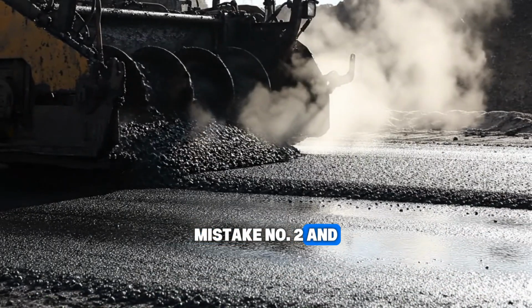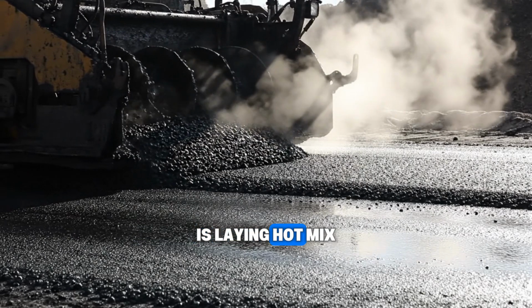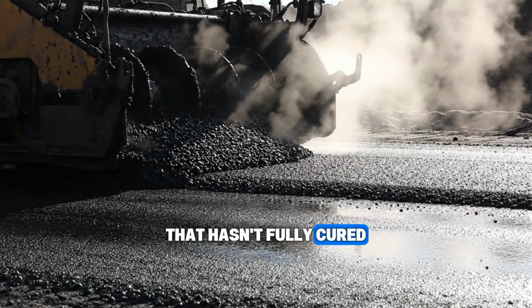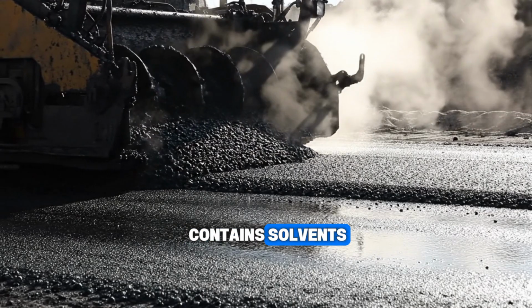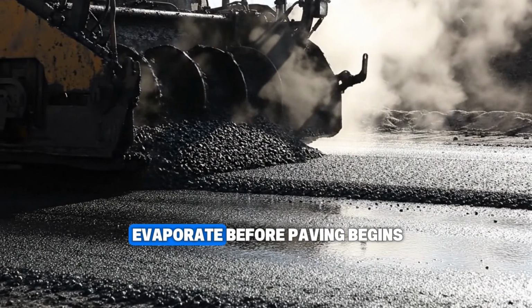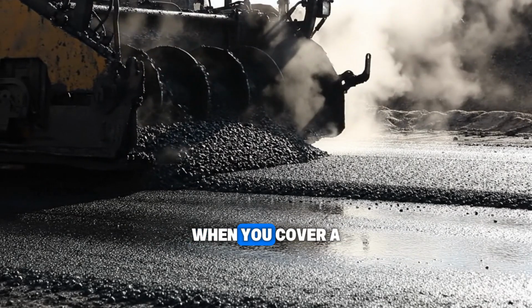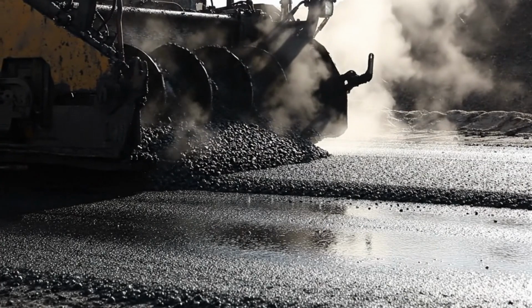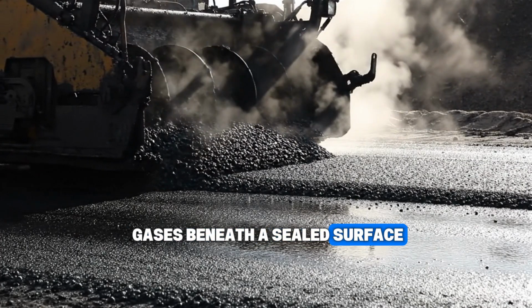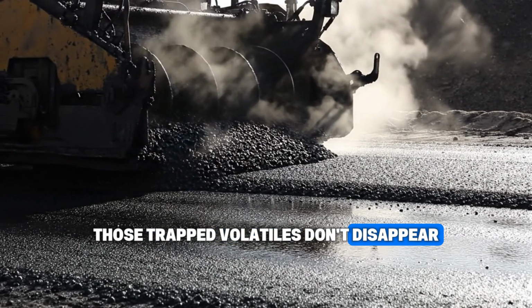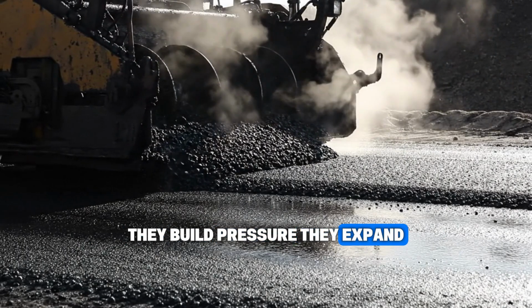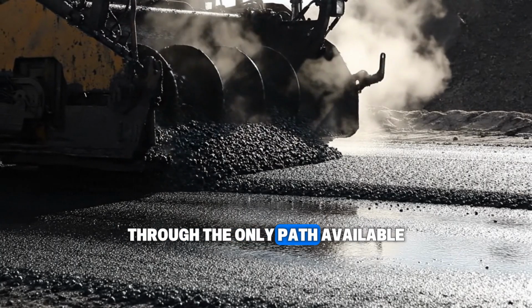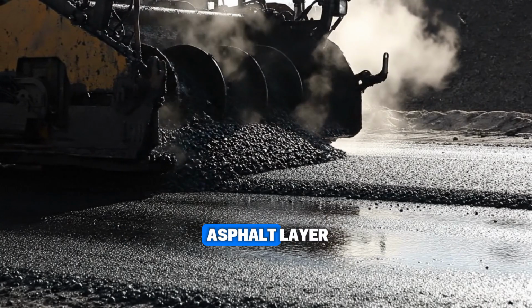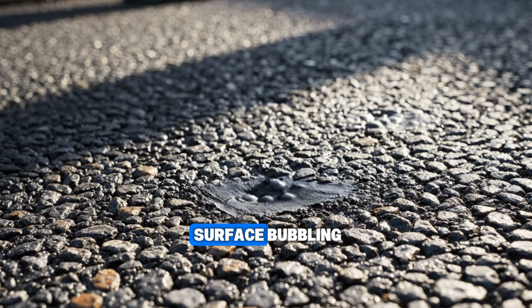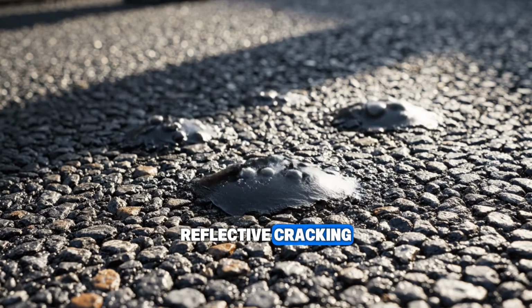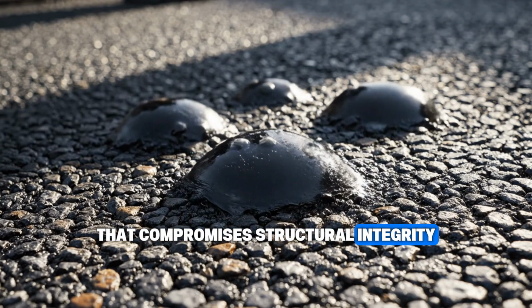Mistake number 2, and arguably the most destructive, is laying hot mix asphalt over a prime coat that hasn't fully cured. A fresh prime coat contains solvents and volatile compounds that need time to evaporate before paving begins. When you cover a green prime coat with hot asphalt, you trap those escaping gases beneath a sealed surface. Those trapped volatiles don't disappear. They build pressure, they expand, and they force their way out through the only path available, upward through your new asphalt layer. The result is immediate surface bubbling, blistering, and reflective cracking that compromises structural integrity from day one.